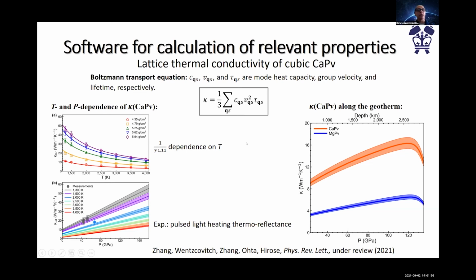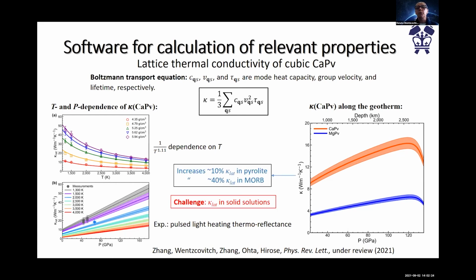And it's a very surprising result, and we asked our colleagues in Japan, Ohta and Hirose, to measure thermal conductivity using pulsed light heating thermoreflectance. They measured at 300 Kelvin, a couple of points at high pressure, and at 2000 Kelvin as well. And the agreement seems to be quite outstanding, better than we expected to achieve. But so here, what is the effect for the mantle? Well, calcium silicate is not a very abundant phase, but it can contribute to an increase in thermal conductivity of pyrolite by 10%.